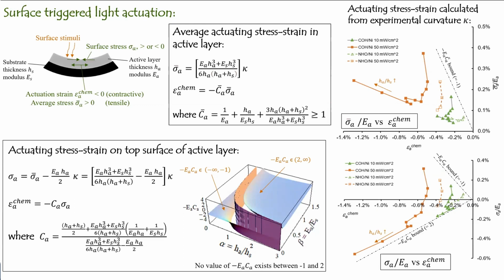And then if you look at this surface, so this CA, which is the compliance, right? You look at the dimensionless version of that, that only depends on the thickness ratio and the modulus ratio. And the surface has two branches. Quite interestingly, there is a singularity line, but there are two branches. So one branch is that the value is higher than 2. The other branch is that the value is lower than -1. So between -1 and 2, there is no value for the CA. So that means that this stress strain curve, because that is the compliance between the strain and the stress, has two bounds.